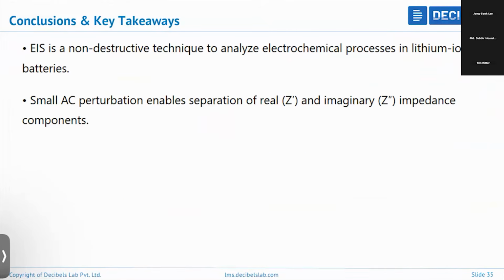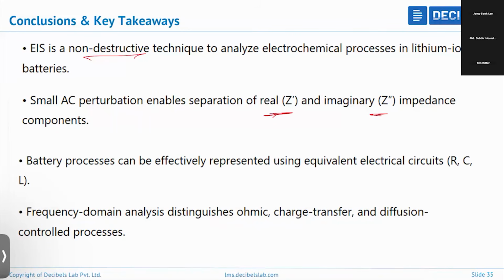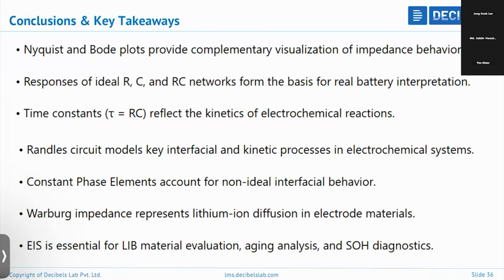So with this, I am concluding my webinar, this bootcamp discussion. In today's discussion, we have understood that EIS is a non-destructive technique to analyze electrochemical processes in lithium-ion batteries. And a small AC perturbation enables separation of real Z prime and imaginary Z double prime impedance components. And battery processes can be effectively represented using equivalent circuits like R, C, and L, sometimes in parallel or series. So the frequency domain analysis distinguishes the ohmic, that is solution resistance, RS, and RCT, and diffusion, the Warburg, etc. Nyquist and Bode plots provide complementary visualization of the impedance behavior. Responses of ideal R, C, and RC networks form the basis for real battery interpretation.